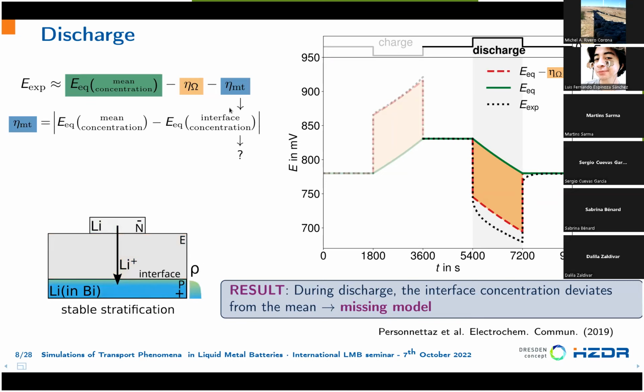And if we just use the equilibrium cell voltage and the ohmic overvoltage to model our experiment, we see that the red line is not able to capture well the black line. There is some additional overvoltage, and this is the mass transport overvoltage that we discussed previously. So there is a difference between the interface and the mean concentration, and we need a model to define the interface concentration.